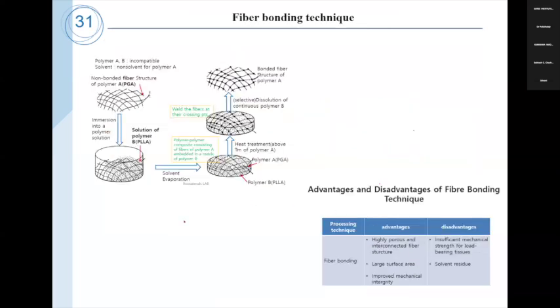The other important technique is the fiber bonding technique. In this technique, first a non-bonded fiber structure of polymer A is simply immersed in another polymer solution, polymer B. After evaporating the solvent, we apply heat treatment above the melting point of the non-bonded polymer structure. After the heat treatment, we dissolve the continuous polymer B. Then finally we can create the bonded fiber structure of polymer A. However, this technique also has some advantages and disadvantages.